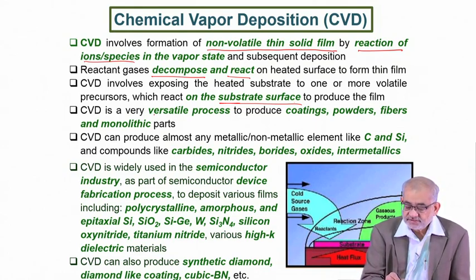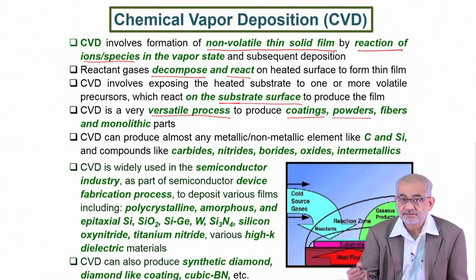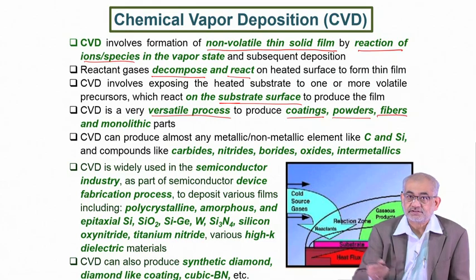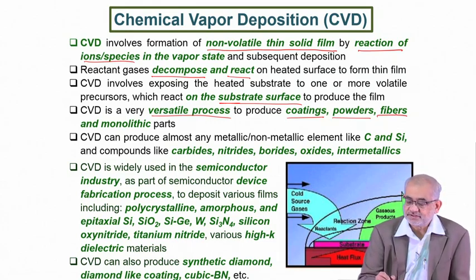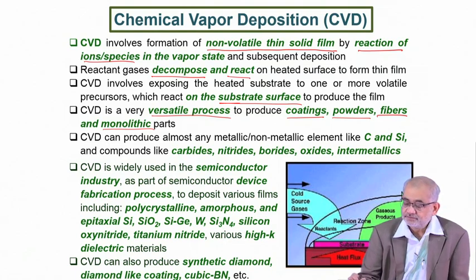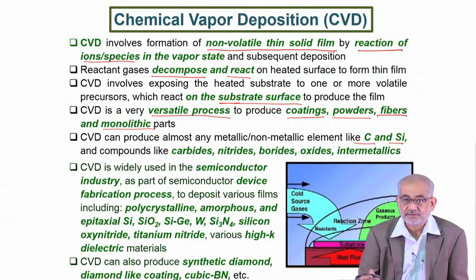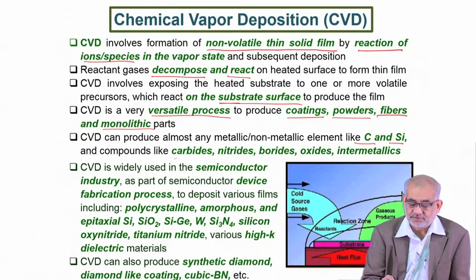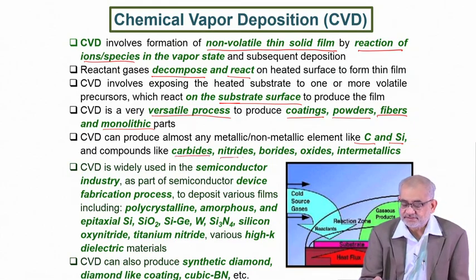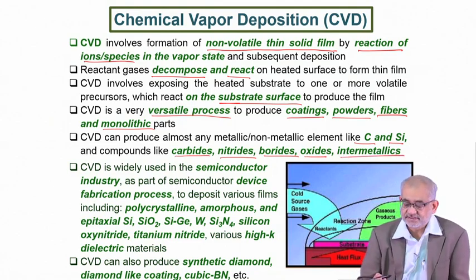This is a fairly versatile process because you can produce various kinds of coatings or films, free-standing powders, fibres with very large aspect ratio, or even self-standing monolithic parts. Compositionally, apart from elemental coatings like carbon, silicon, titanium, or chromium, compounds are also possible — various carbides, nitrides, borides, oxides, and even intermetallic phases like aluminides and silicides.